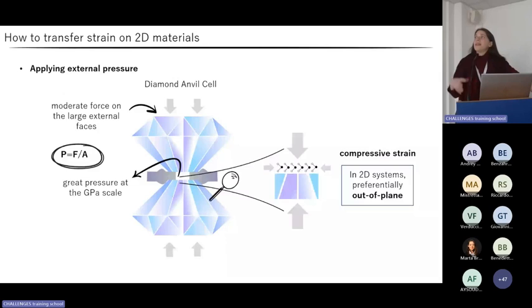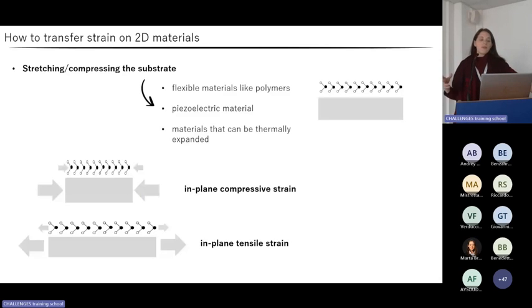If we want to apply an in-plane strain, then we have to transfer our low-dimensional flake onto a proper substrate, for example, a polymer or a piezoelectric material, which can be compressed or stretched in one or two directions so that we can obtain an in-plane strain, biaxial or uniaxial, compressive or tensile.